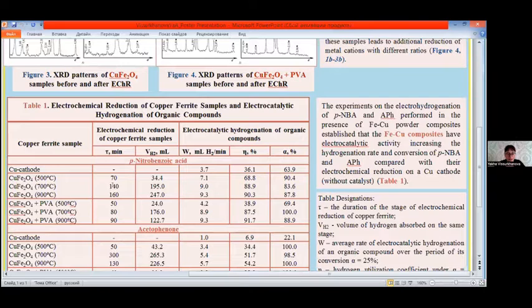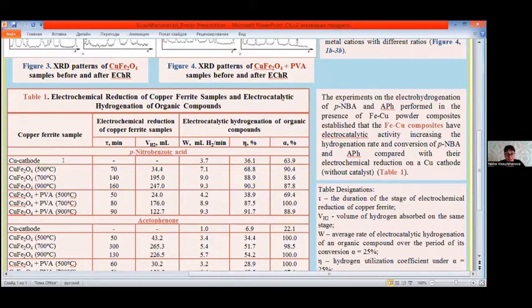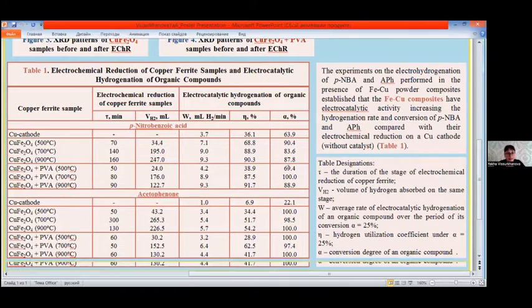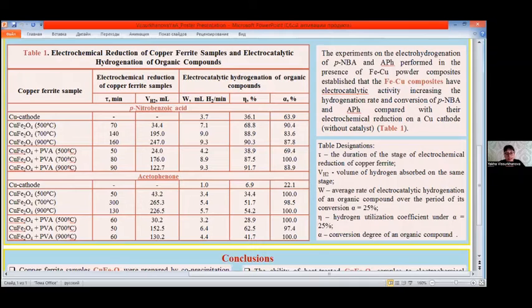It can be seen from the table that the hydrogenation of nitrobenzoic acid on the copper cathode without catalysts occurs with a rate of 3.7 milliliters of hydrogen per minute, and the conversion degree is about 64%. It should be noted that the hydrogenation of this acid using copper ferrite samples significantly increases the rate and conversion degree of these organic compounds. In the case of the electrohydrogenation of acetophenone using samples prepared with salt and with polymer addition, the rate and conversion degree also went up compared to its electrochemical reduction on the copper cathode.